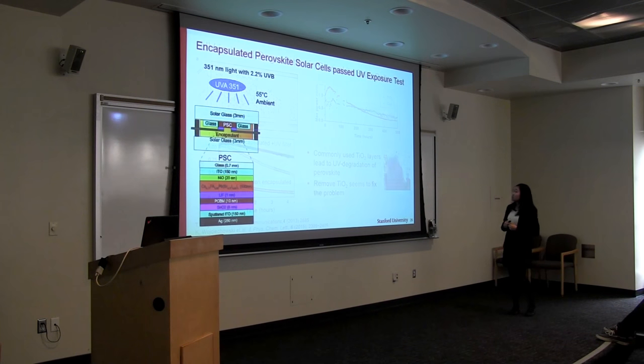So looking at my stack, I took my stack, packaged it in the typical glass encapsulation, and I shined a UV light with a 350 nm light on. By doing this, I heat up my package to around 55 degrees Celsius, and this test is done in ambient. One design change I made is that I removed the encapsulant between the perovskite and the solar glass to try to get the maximum UV onto my perovskite solar cell.